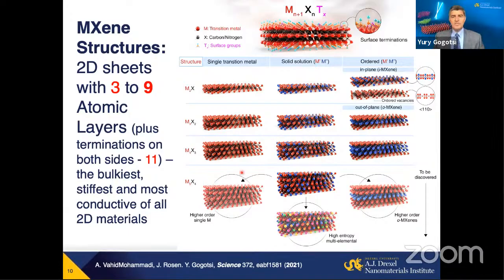if you look at about 10 different transition metals used, carbon and nitrogen, you end up with possibly 100+ combinations with which you can design the structure. If you multiply it by about 10 different surface terminations demonstrated so far, you have about 1,000 well-defined structures. But now you can make a solid solution on the M side and a solid solution on the X side. And recently, this year, already 3 research groups have demonstrated high entropy multi-elemental MXenes.